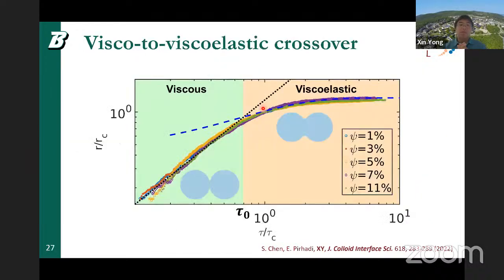More importantly, by using this theory, we can now collapse all our simulation curves onto one master curve, as we can see here. And so then there are two regions characterized by this master curve. One is a viscous linear region, and then a viscoelastic curve. And so the intersection of these two lines will determine a crossover characteristic time, which dictates this viscous to viscoelastic crossover. And this is the first time that these particular transitions between two regimes have been reported.